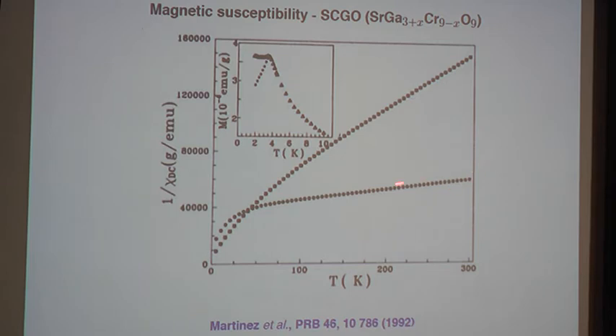But the important thing is that we can extrapolate this high temperature behavior down, and it crosses the axis at a temperature of minus several hundred Kelvin, showing that we have really strong interactions. But at the same time, we can cool down to temperatures far below the interaction scale, and the inverse susceptibility is a smooth function of temperature, suggesting that there's no phase transition.